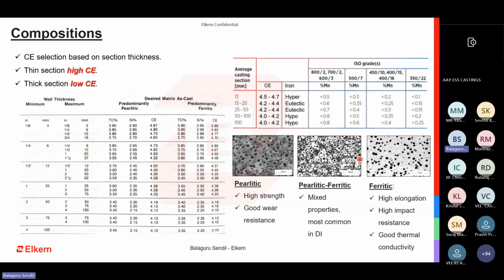We will be more than happy to develop certain grades which do not fall within this particular slide's purview, where we have high silicon and low carbon kind of grades. Then the carbon equivalent slightly differs. The methoding and risering slightly differ for that. The treatment of inoculation as well as nodularization is also different for that.